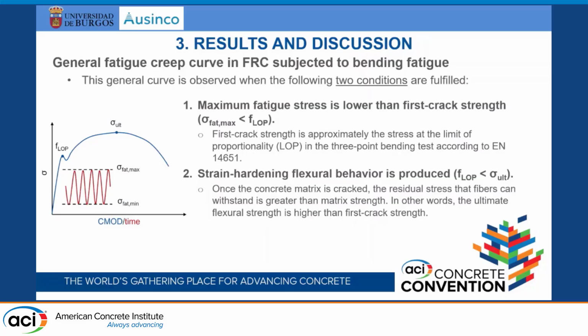So what are the conditions for having this double S curve? Well, two main conditions. First, the maximum fatigue stress has to be lower than the first crack strength. That's one of the points. And the other condition is that a strain hardening flexural behavior has to happen, or more precisely, the residual strength after cracking has to be higher than the maximum fatigue stress. So those are the two conditions for having this double S-shaped curve, the general case of the fatigue creep curves.